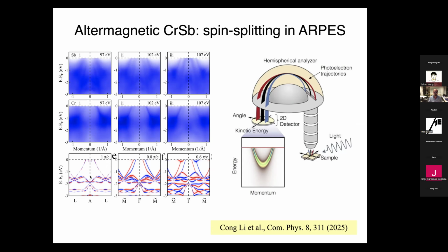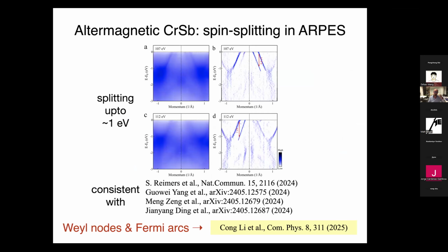And you see here that here's the calculation. For this value of the incoming energy, at this kz, there is no calculated splitting, the bands are almost degenerate, which you also observe. And for different values of incoming photon energy, you measure at different momenta, and you can see that there's the spin splitting of the bands. The spin splitting is large, up to 1 electron volt. You see it more clearly here. And this is the same spectrum, but it's the second derivative of that spectrum. And you see clearly that there is this large spin splitting, which is consistent with other reports in the literature.